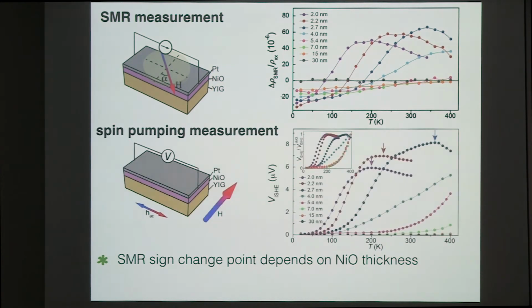But if you compare it with the corresponding spin pumping experiment, which tells you the spin transmission in all these samples, you will find something very interesting. First, there is good correspondence of the peak position. Basically, we know that this peak means the Néel temperature, which means the SMR will be maximized with positive sign around the Néel temperature. So this is easy to understand.